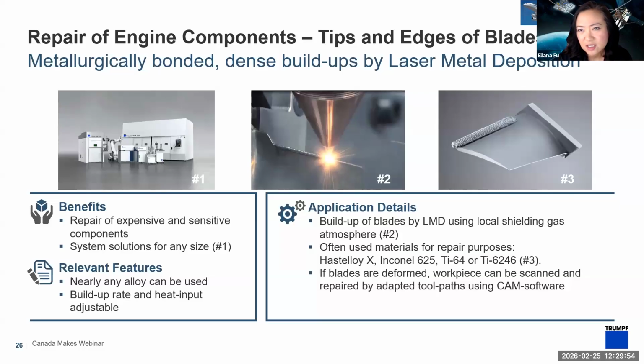You just have to adjust the build rate and the heat input. So here's an example of creating blades. This is for aerospace, using a local shielding gas and then repair. I think this was demonstrated actually years ago on a Rolls-Royce seal segment, but it can extend to any kind of structure that you can imagine.